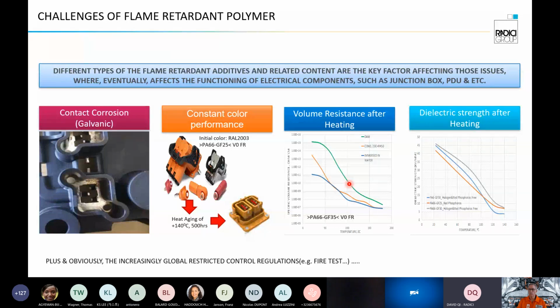And then I would say in the future, there are 2 aspects that customers did not focus on in the past, but nowadays we are constantly and seriously requested by customers to pay attention to the volume resistance and also the dielectric strength after heat aging. And you can see here, this is our polyamide 66 filled with 35% glass fiber, V0 grade, which is halogen free and also red phosphorus free.